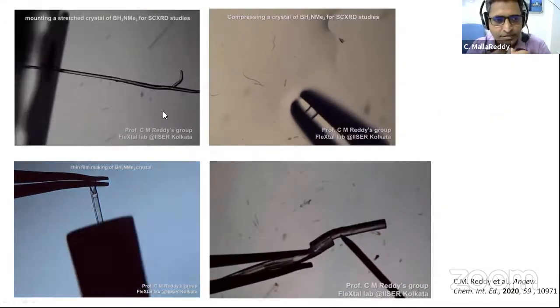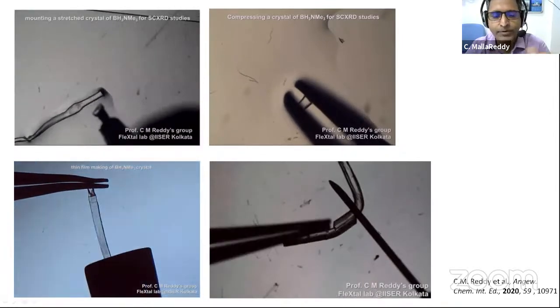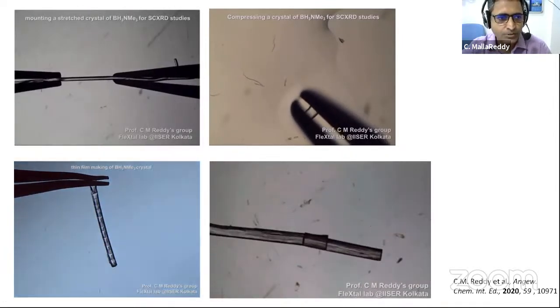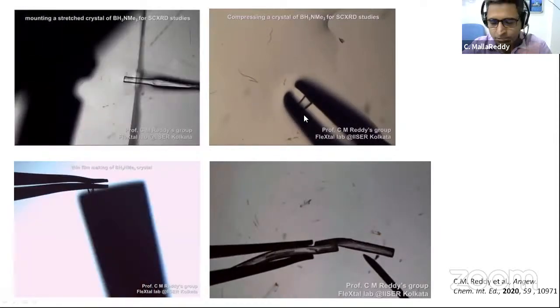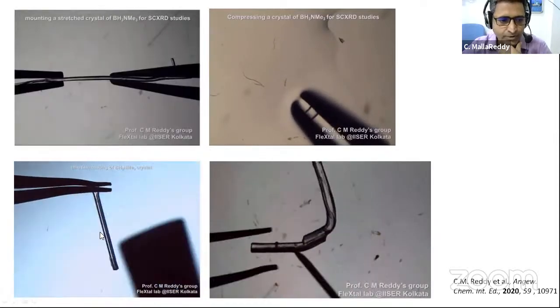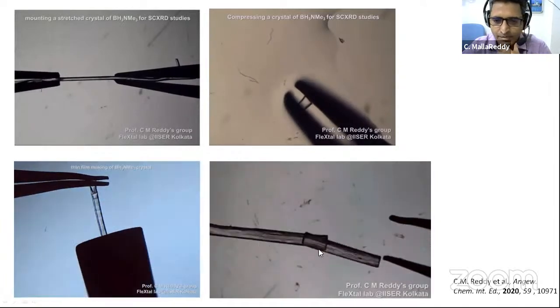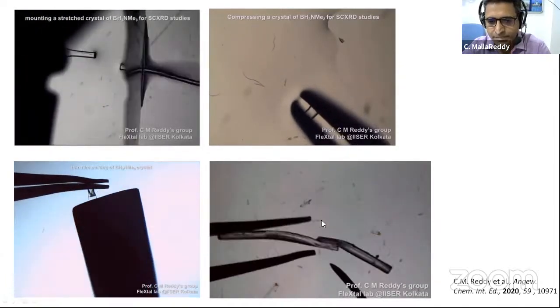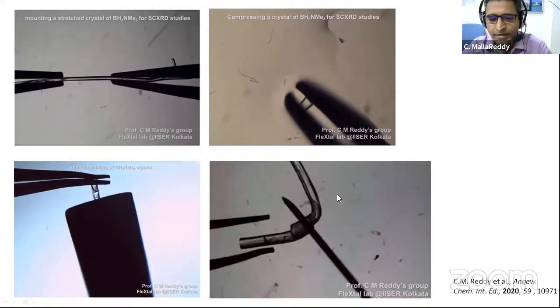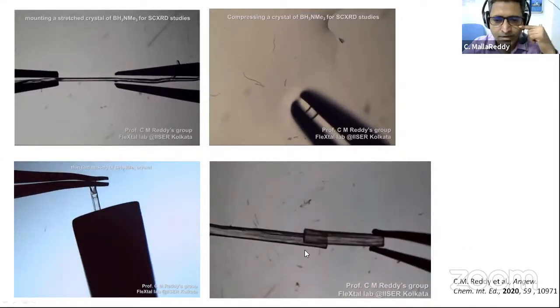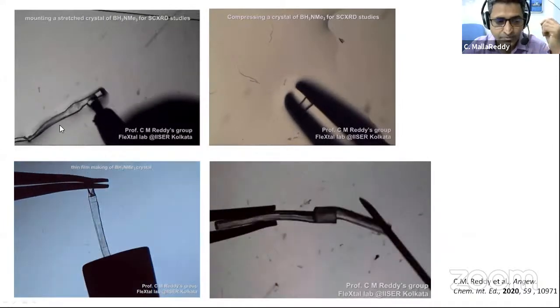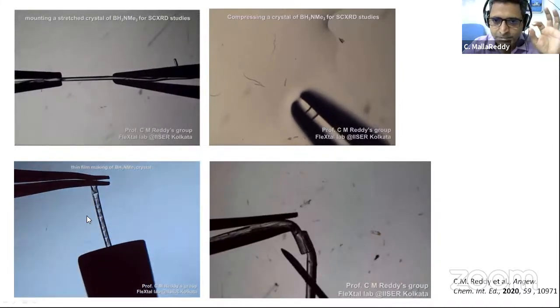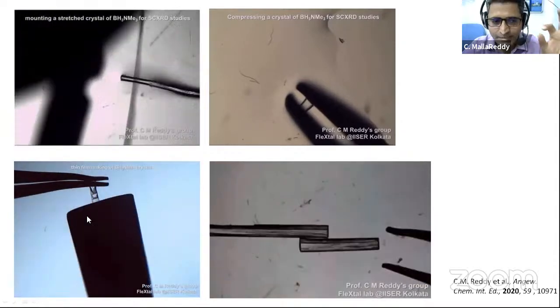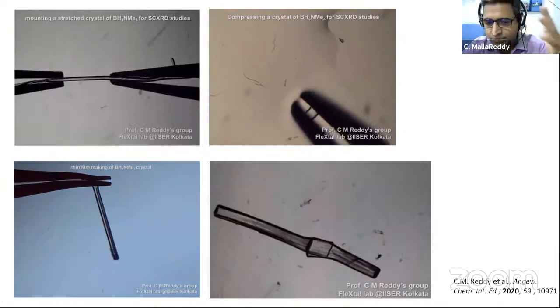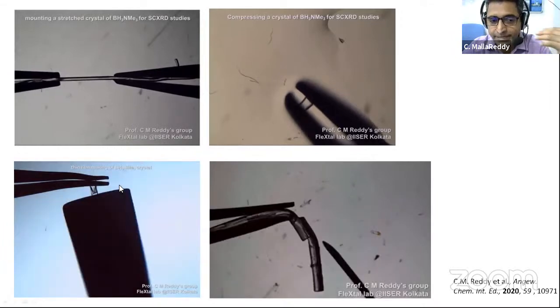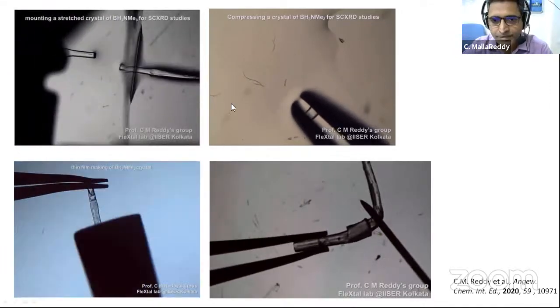And then you also have crystals which you can pull, like a copper wire, for example, at high temperature. And this was also totally unknown in molecular crystals. Then you can compress them, you can also make them into thin films, and you can put crystals together and compress, then they stick to each other, a kind of mechanical welding. But here the most important thing is in all these cases, even after extreme deformation, if you take a nice piece of crystal which is transparent and clean, and put it under a diffractometer, you can get the single crystal data. So that means it retains the crystallinity very well even after deformation.